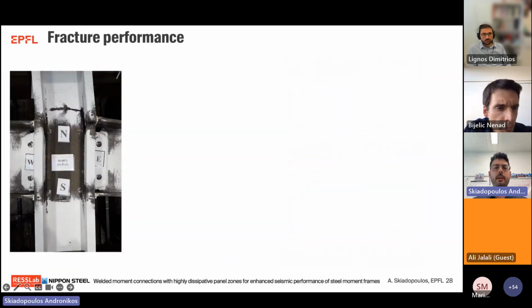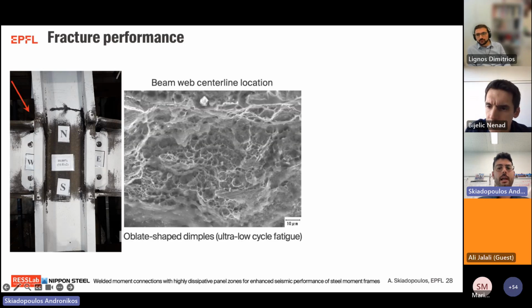Scanning electron microscopy in the test specimens highlighted that the failure mode involved ductile crack initiation and also propagation due to ultra-low cycle fatigue. And here we saw a characteristic sample of the scanning electron microscopy in the middle figure, obtained for the column flange fracture surface near the beam web centerline where fracture initiated. And from the oblate shape of the dimples, it is confirmed that fracture was caused due to ultra-low cycle fatigue.